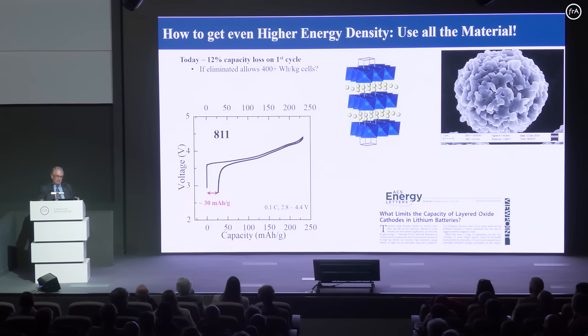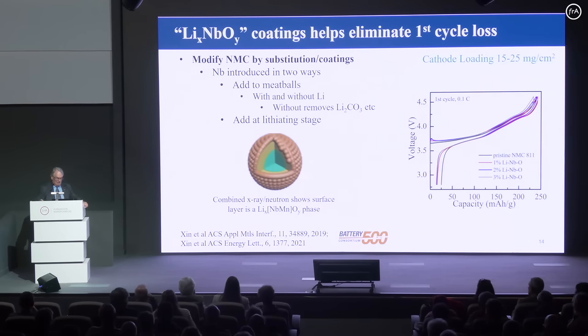So we decided we should be able to modify these materials so we can get it all in, and we've had some success by modifying them by either coating the surface or putting atoms inside. We stabilize this lattice, which stops this oxygen release, and the material we found best for this was, in fact, niobium. We put 1% niobium in these materials. Part of it stays on the surface, part goes into the lattice. But in reality, it's quite a lot more complicated, because when the niobium goes in the lattice, some of the manganese comes out. So the surface coating is, in fact, a niobium manganese mixed oxide. And you can see from the plot on the right-hand side there, we've reduced that first cycle loss by about 50%. Our goal is to totally reduce it.